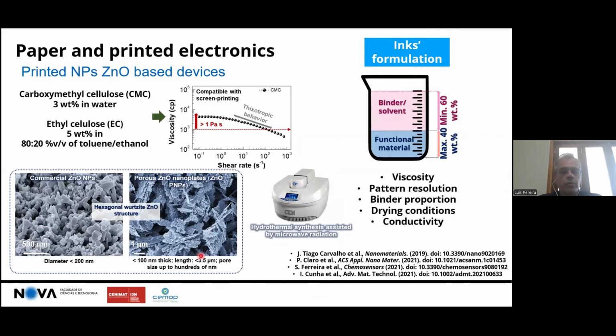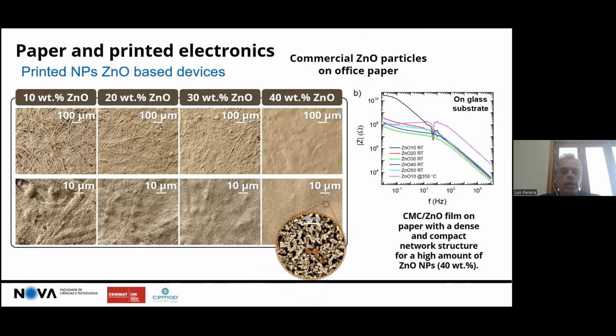Another thing that you can do is also play with the shape of the particles. So we are using spherical or close to spherical zinc oxide nanoparticles, but you can also go for nanoplates. So you can also synthesize zinc oxide nanoplates by playing with hydrothermal synthesis of these plates. And you can use either spherical or nanoplates, and the ink itself that we developed is based on the mixture of carboxymethyl cellulose and zinc oxide, either the nanoplates or the nanospheres.